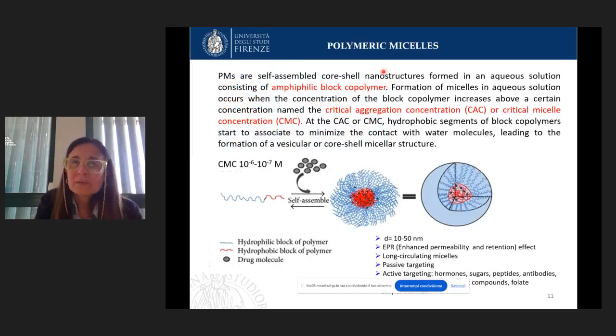Another carrier is polymeric micelles. Polymeric micelles are self-assembled core-shell nanostructures. These micelles are made of amphiphilic block copolymers. In the amphiphilic polymer, we have a hydrophilic portion and a hydrophobic portion. The hydrophobic portion, above the critical micelle concentration, produces a hydrophobic core. Inside this core the lipophilic drug can be loaded, and around the core there is a hydrophilic shell. The dimension of these micelles is between 10 and 50 nanometers.